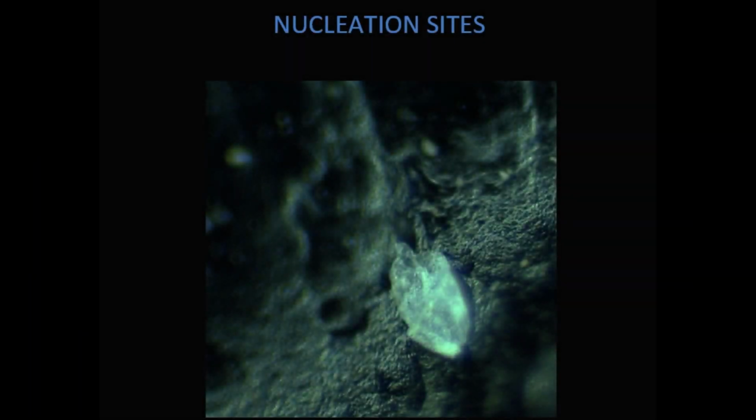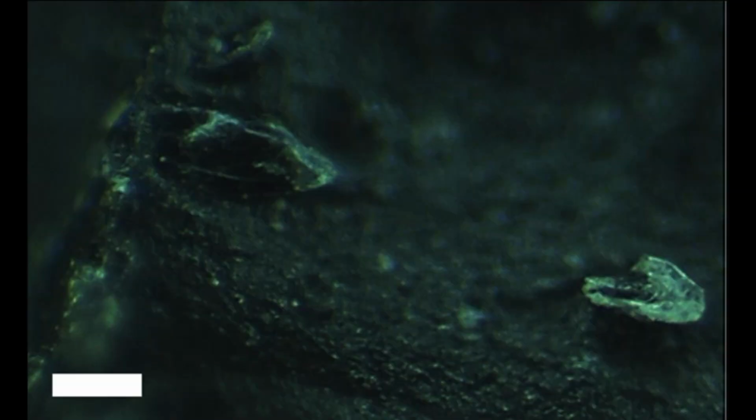Nucleation sites are impurities, like suspended particles or minute bubbles in a liquid, resulting in heterogeneous nucleation. In splash-form tektites many surface bubbles on shells contain partly melted quartz grains, embedded in their inner surfaces.